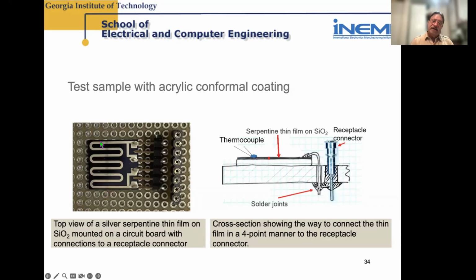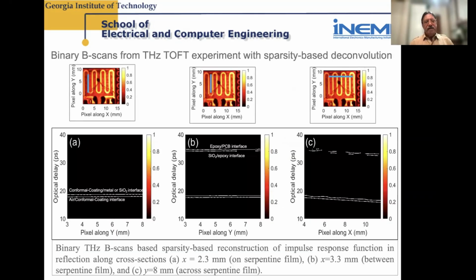If the conformal coating is too thin, it may not protect the underlying material. If the conformal coating is too thick, it might stress the underlying material or be too difficult to remove should repairs be required. So here's some examples, and here we are going to show B scans. The first on the left, A, is along this metal at a position on top of the serpentine metal. The B is between the metallization, and C is across.